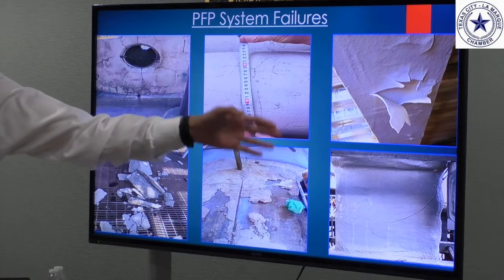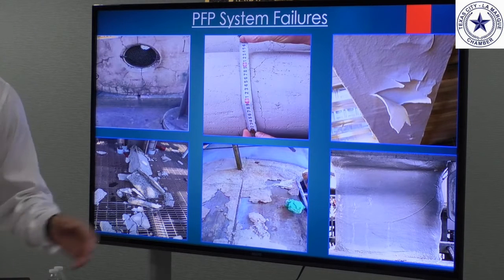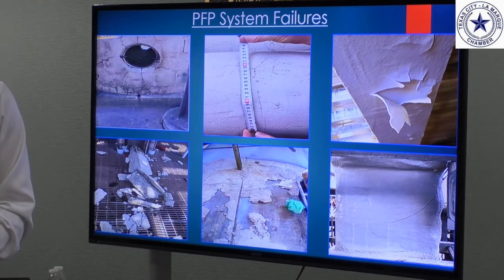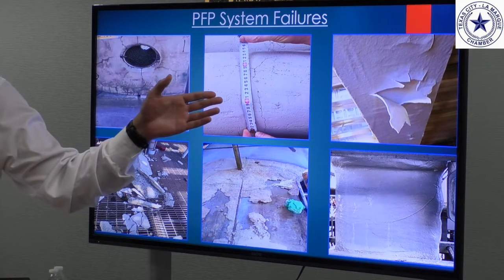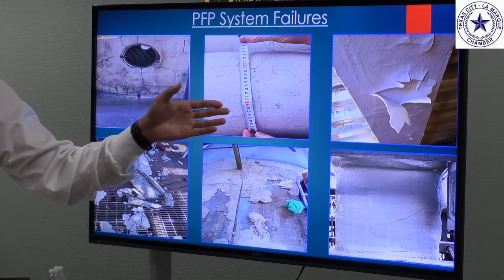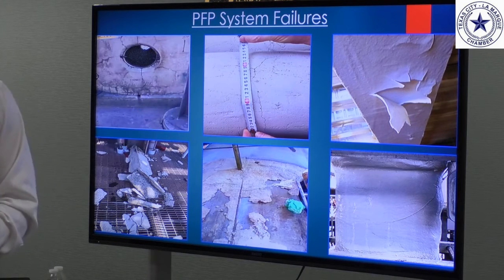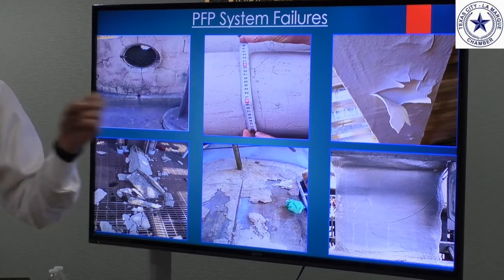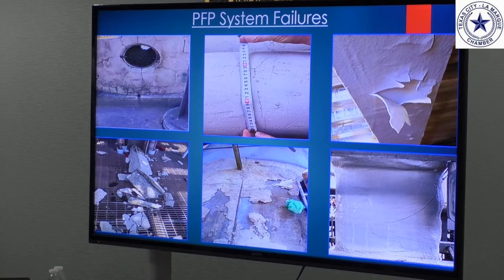The last column is epoxy intumescent. So the first photo looks like it was some solvent entrapment that blistered up, and this is due to poor application and overcoating too quickly. You do have to allow the solvent to flash off before you put that second coat on. This created a blister because that solvent wants to escape out. So that blister continued to grow, and then eventually it damaged the coating. So now we have to go back and effect a repair.